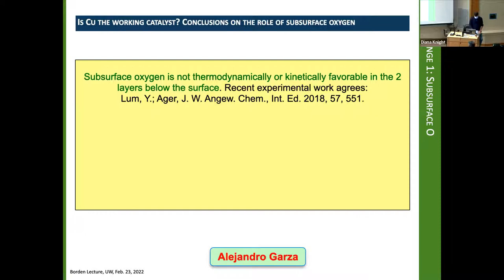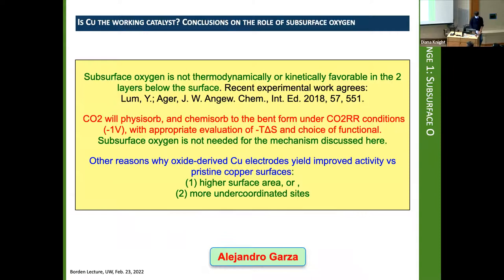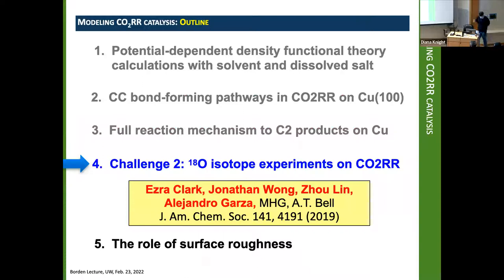And I guess I will skip this, but oxide-derived copper electrodes are interesting because essentially you get a higher number of low coordination sites and a higher surface area, and that can give improved activity without the necessity to have an oxide involved. Okay, there was a second challenge. This is a quite interesting one, and as you might notice, we got a J. Phys. Chem. Lett. paper out of responding to the first challenge. We got a JACS paper out of responding to the second one. So this was altogether a quite productive interaction.